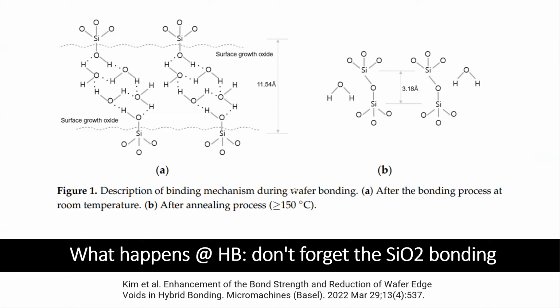During wafer bonding, the bonding mechanism: if the surface oxide is initially a wavy structure, the oxide bonding is different, and this is your surface treatment. This surface treatment by plasma activation is initially about 12 angstrom thick, and with an anneal, you hopefully could form a nice bond like this. It becomes a regular SiO2 bond, about 3.2 angstrom.